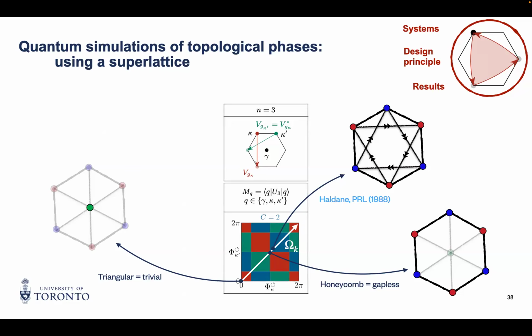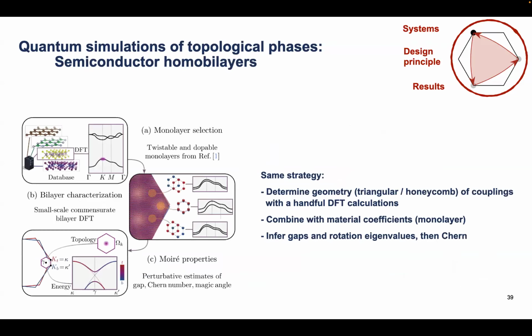So out of the triangular lattice, it's very hard to stabilize the topological phases. I stay in the red regime, which is trivial. But as I add a tiny bit of Berry curvature to the honeycomb lattice, then I end up in a topological C equal +1 or -1, depending on the sign of the Berry curvature. And that reproduces the original result by Haldane. So you're talking about introducing a Berry curvature to the monolayer? Yes, exactly. Not the superlattice. So that would be in the form factors of the monolayer that you put in this calculation. Yes. All right.